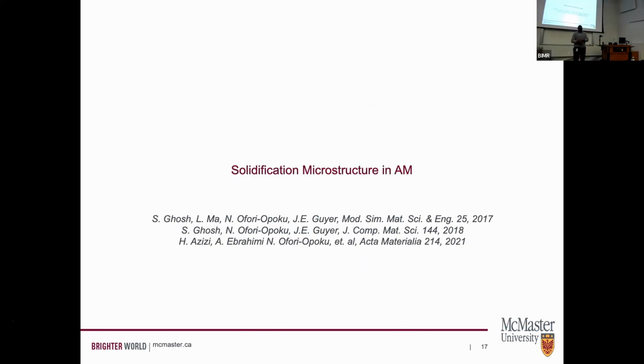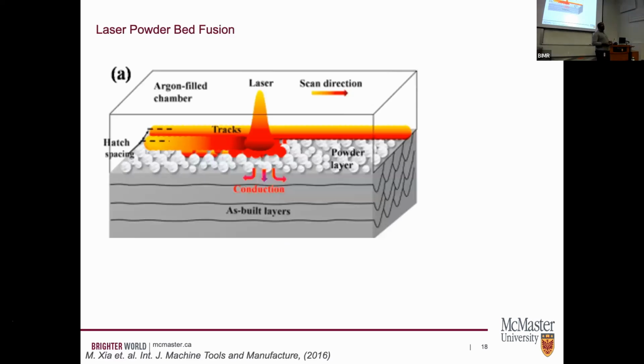So now let's get into how we apply these phase field models to microstructure evolution, and let's start with additive manufacturing. So additive manufacturing, for those of you that are aware, is a new manufacturing technique that uses powder, and it does it layer by layer. And so you lay down your powder on some substrate, you have some energy source, could be a laser, electron beam, you raster it, the powder melts, you add the next layer of powder, energy source, it melts, and you do this layer by layer.